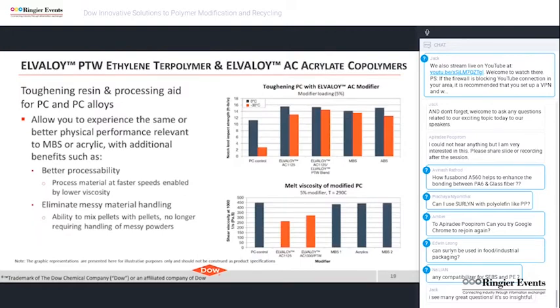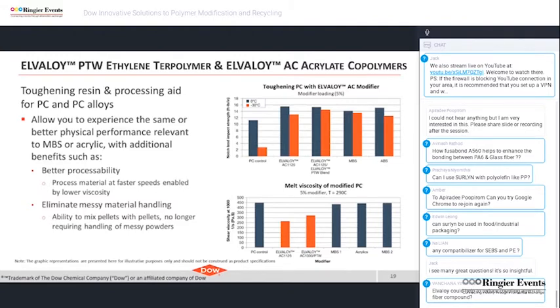PC is a good engineering plastic and has good toughness above 0 degrees centigrade, but below minus 10 degrees centigrade impact is poor. The top right chart shows the toughening of PC with Elvaloy AC versus MBS and ABS modifiers. We can see that Elvaloy AC and Elvaloy AC PTW blend shows better impact at 0 and minus 30 degrees centigrade than PC control and comparable to MBS and ABS. The bottom right chart shows the melt viscosity of modified PC.